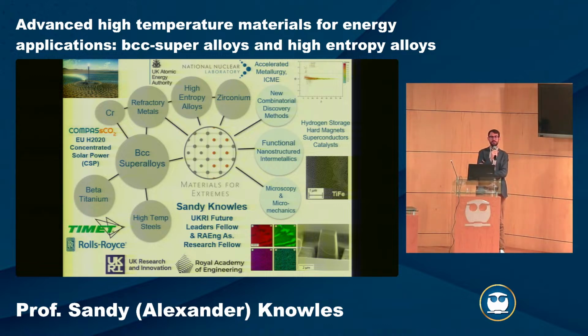Yeah, it's an important one. In BCC metals in general, we have the brittle-ductile transition. So your matrix is not an ideal starting point for something with ductility, because you have to tune and choose the element of the base metal. Chromium or tungsten has a brittle character at room temperature because of dislocation behavior. You can potentially do alloying additions, which can change that, so you can improve the matrix behavior of the BCC metal. We have the same challenge in the intermetallic. In that one, it's potentially an opportunity as well, because we ideally want the same deformation mode as the BCC metal, where we have these 1/2<111> dislocations, which can give us ductility.